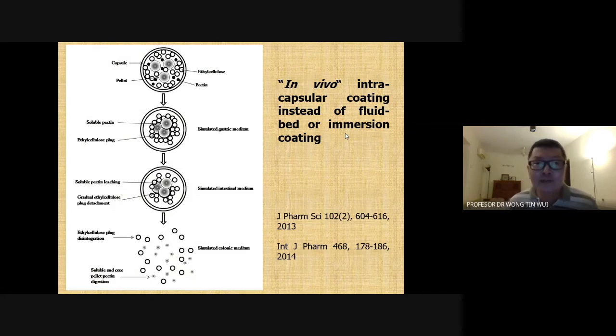Now, how to achieve that? Basically, in this study, we use 5-fluorouracil as the drug of interest, and we encapsulate the drug in pectin-rich pellets, and we fill the capsules with the pectin-rich pellets together with the coating material, which is made from ethyl cellulose and pectin. Now, upon ingestion of the entire capsule orally, in the gastric region, the dissolution medium